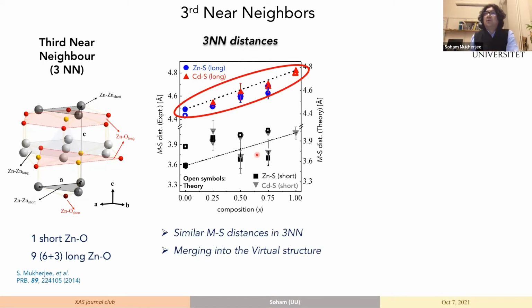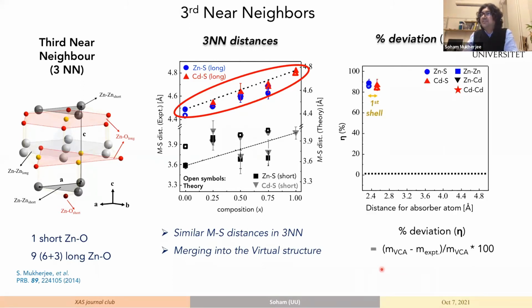Now, when we compare the percentage deviations as we calculated from this particular equation, where we calculate the slope of the experimental values of these distances normalized by the virtual crystal line, we see from the first shell, which Matt was asking about, that this deviation was extremely high. The moment we go to the second shell, there's a sharp reduction in the value of the deviation, and you can see that the description has come much closer to the zero line.